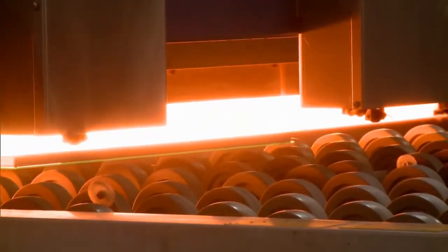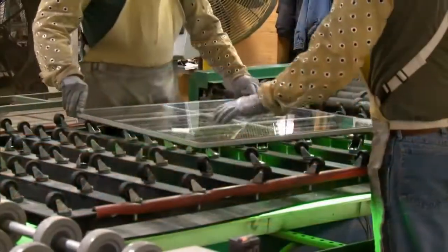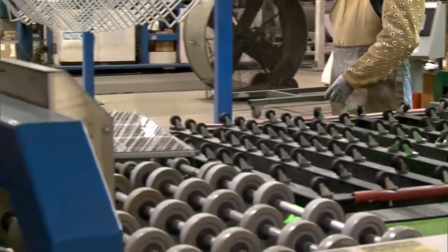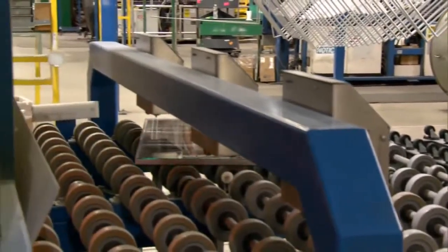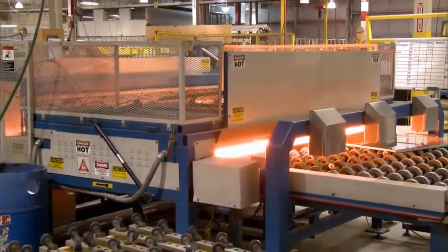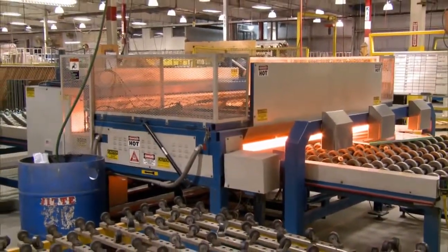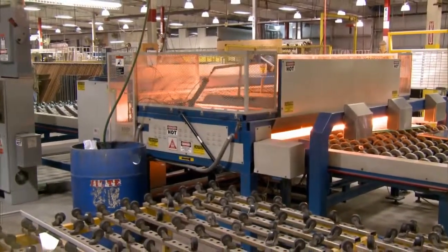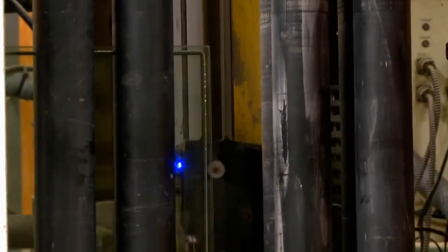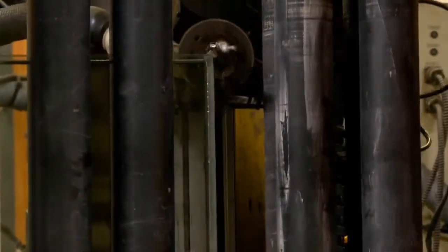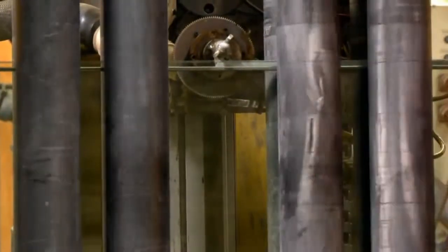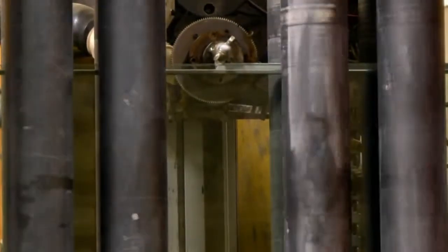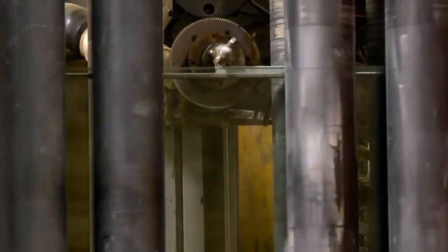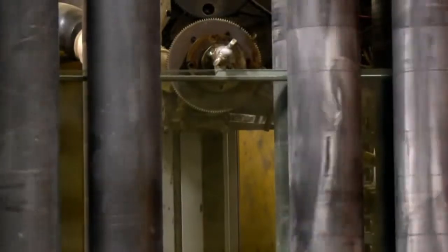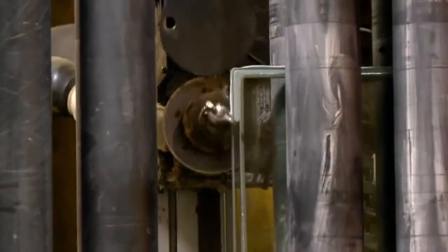it is moved into an oven to be heated to a sealing temperature. Once the unit reaches the exact temperature, rubber rollers press the glass down to its specified insulated glass thickness. This process also makes a more reliable seal by pressing the butyl deep into the pores of the glass. Our glass cutting processes, combined with our sealing process, work together to ensure that our insulating glass units are virtually failure-proof and built to last for years.